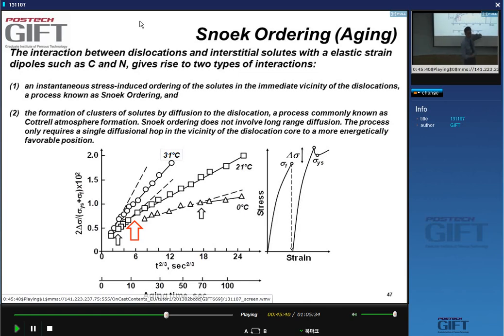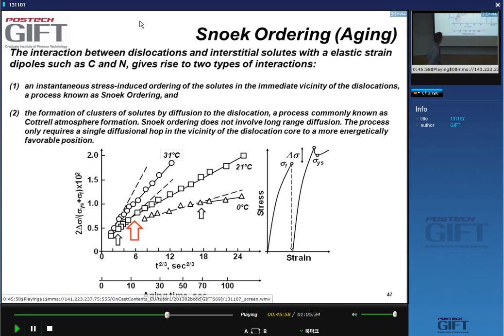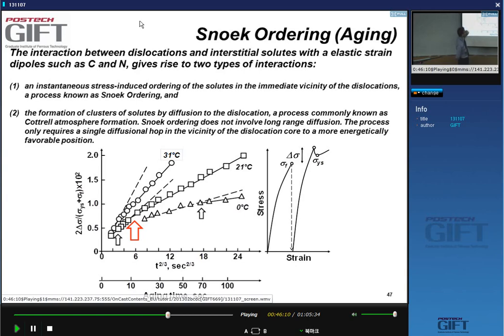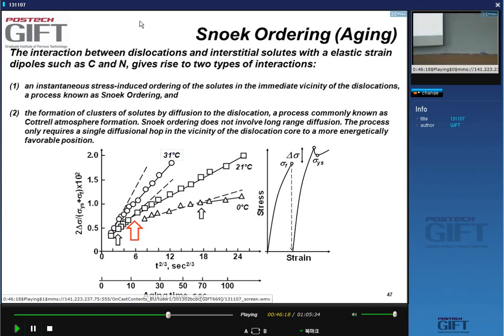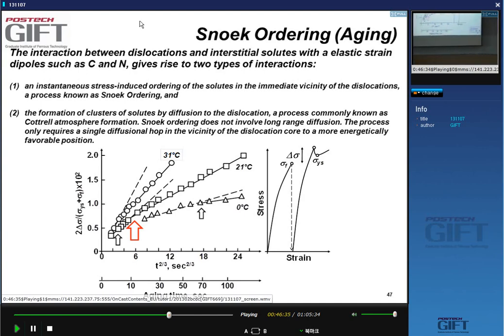If you deform a carbon steel, then stop and repeat after a few seconds, you suddenly find a yield point. You can look at the kinetics of this process — the change in the increase of yield strength over time. It takes about 10 seconds to get a very pronounced yield point. You can relate these kinetics with the time for a single diffusional hop — in this case for nitrogen — and the kinetics of maximum Snoek aging match.